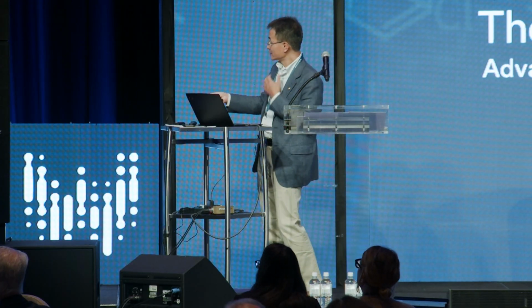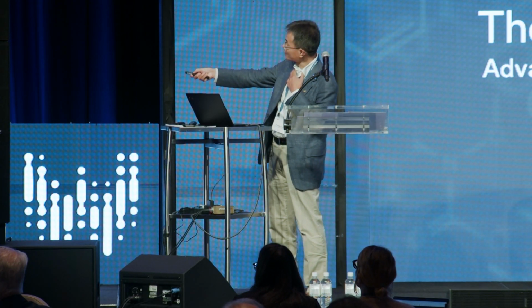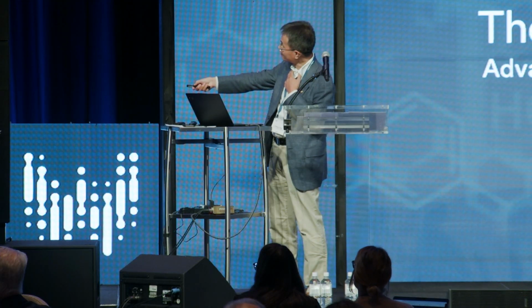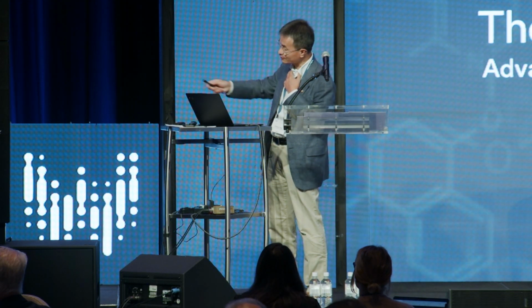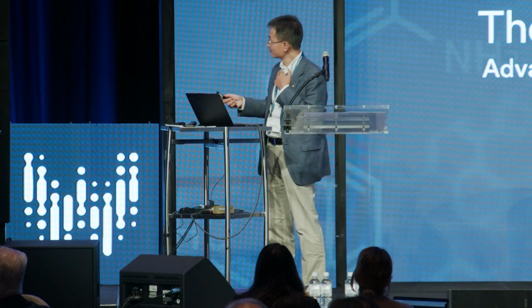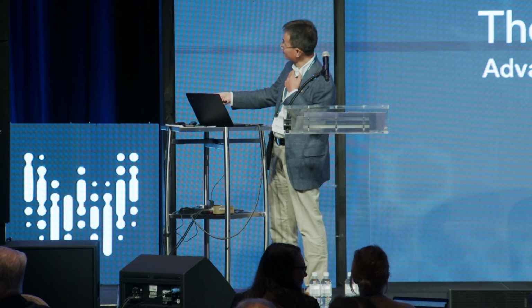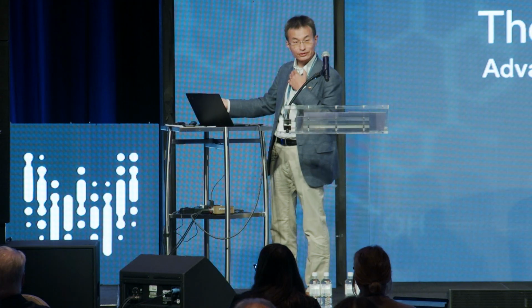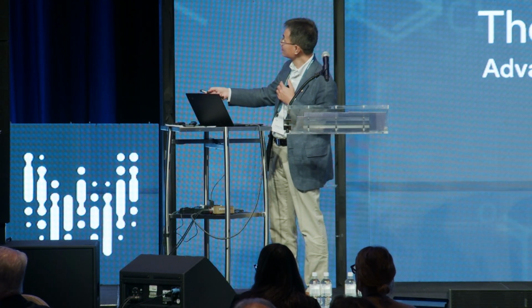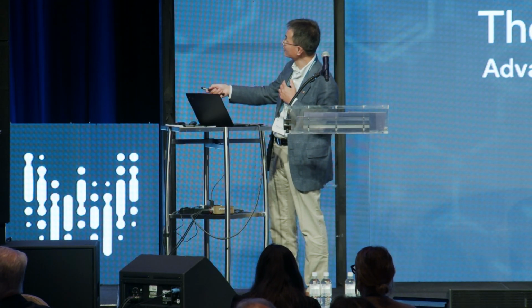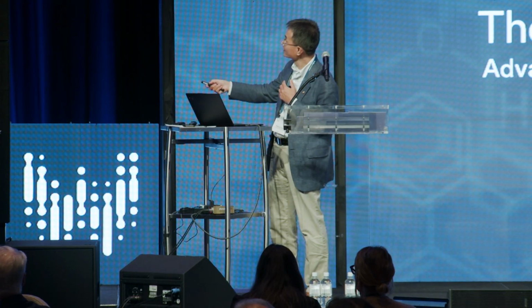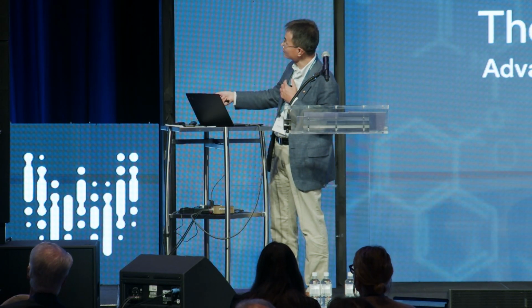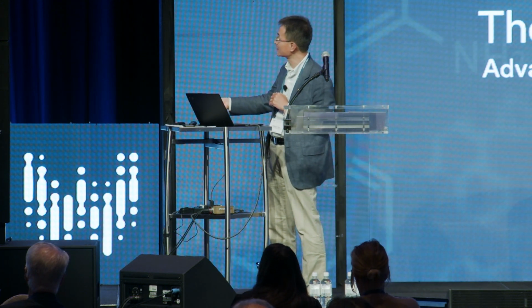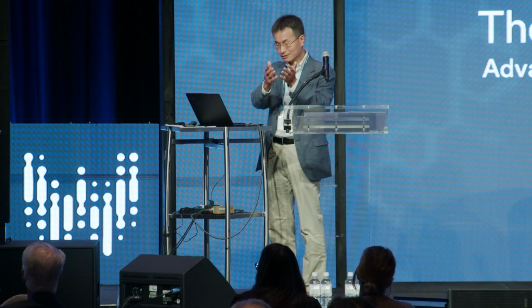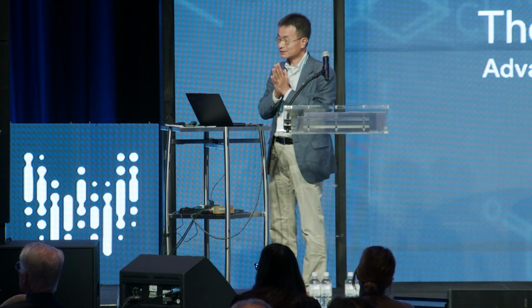This is temperature-dependent thermal conductivity, right? You can see the thermal conductivity is going down as we drive down the size of these nanowires. Let me put a reference: bulk silicon is a very good thermal conductor. At room temperature it is 300 watts per meter Kelvin, somewhere here. When you are working with silicon nanowires, you can see thermal conductivity is significantly decreased, even below 10 watts per meter Kelvin. This is not surprising. Certainly, Mingo predicted that early on.